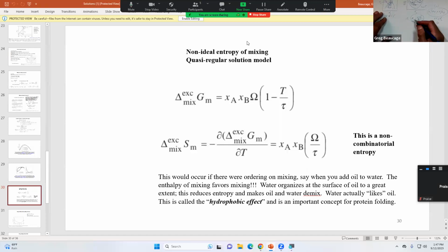So if instead of having 1 over T, you have A12 as some constant, call it A, and then call it B over T. In that case, you can make it mix at high temperature, so B is a negative number. And if it's a polymer, this is divided by N, so that goes to 0 basically. If N is 100,000, there's no entropy of mixing. There's no randomness, because there are just a few polymers in there. There's not enough entropy to drive the mixing.